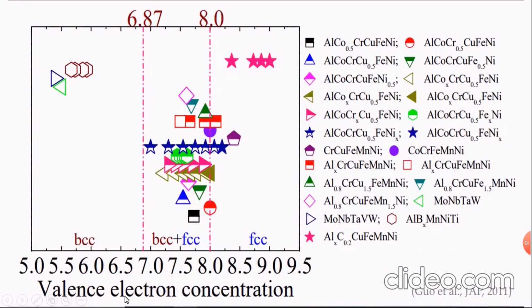If you see here the plot of valence electron concentration for your system, here are examples of many high entropy alloys. You can see that in a certain range of total valence electron concentration, we have BCC. In another range, we have BCC plus FCC. If you exceed a valence electron concentration of 8, you can have only FCC. So, depending on the total valence electron concentration, you have different high entropy alloys.